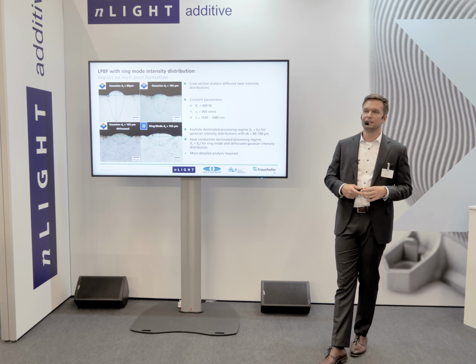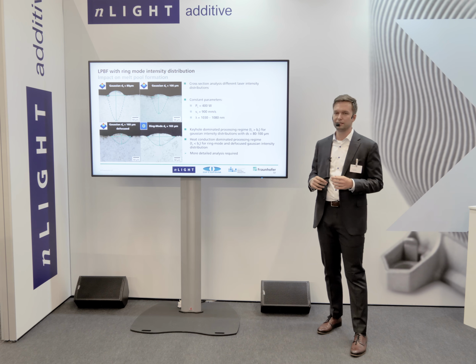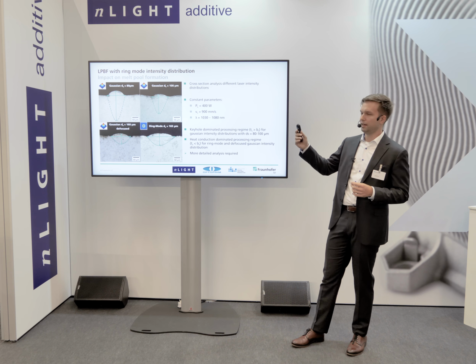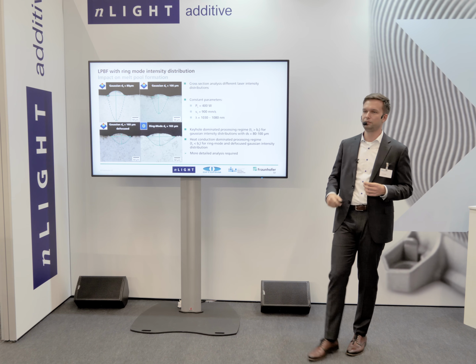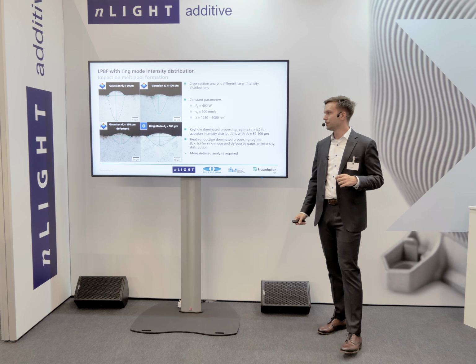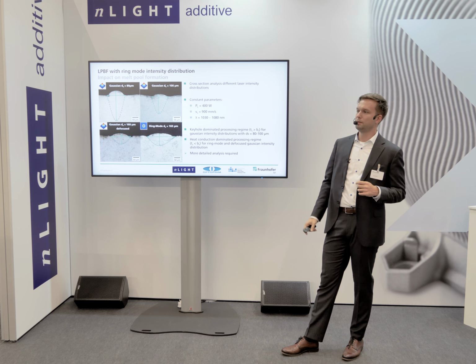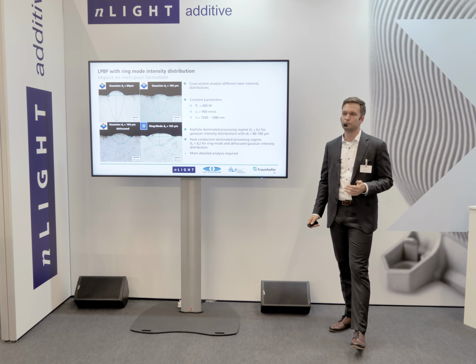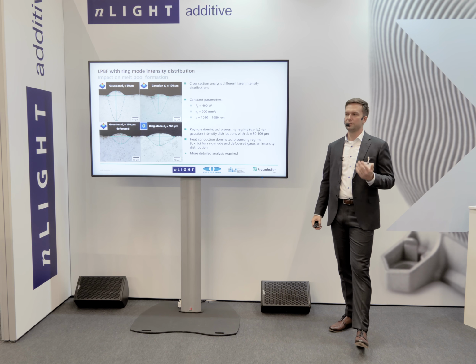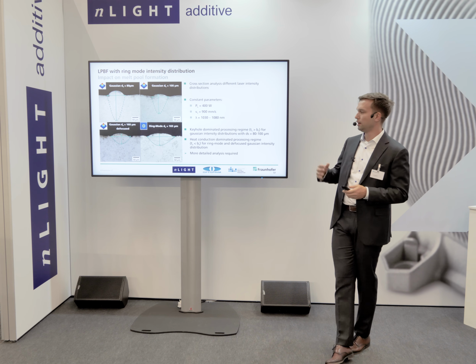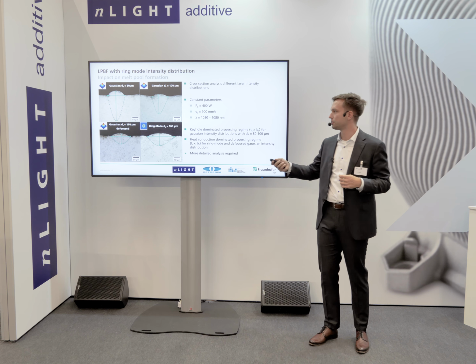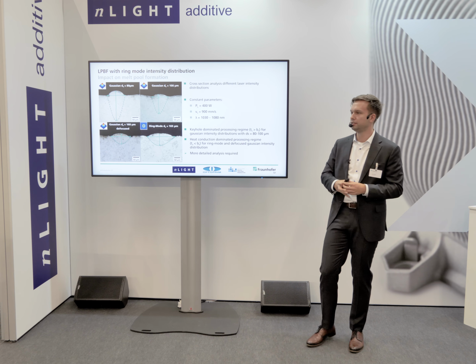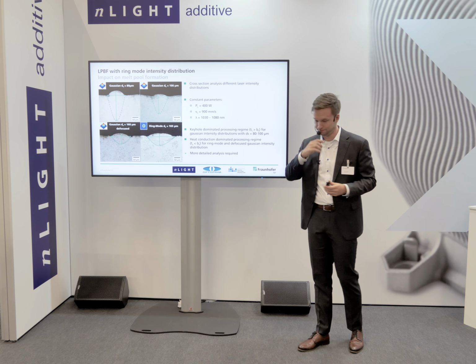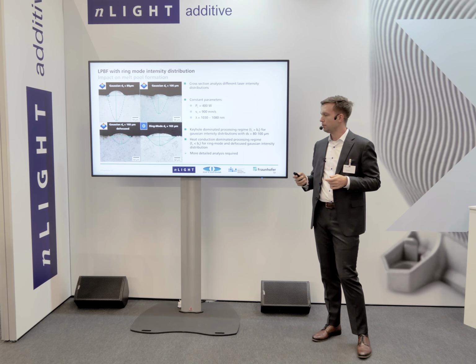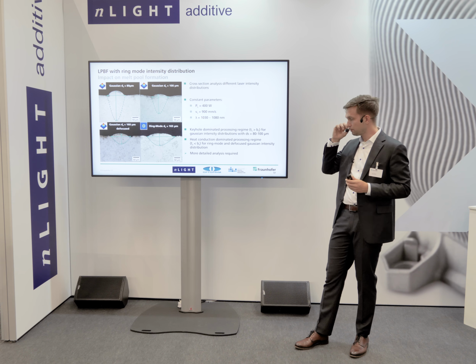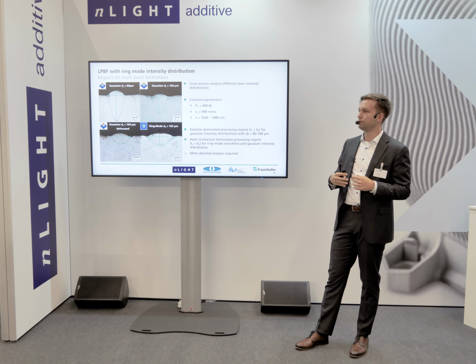So now on this slide you can see some results for these intensity profiles for same processing parameters but different intensity distribution and beam diameter. And you can see clearly that for the smaller beam diameters Gaussian, you have a more keyhole dominated process, so very deep and narrow melt pool with a risk of keyhole pore formation, and the difference is very apparent. So for the small laser spot sizes, Gaussian intensity distribution, very strong keyhole formation. And for the larger beam diameters, ring mode and Gaussian, you have a more heat conduction dominated processing regime, flatter melt pool, wider melt pool.